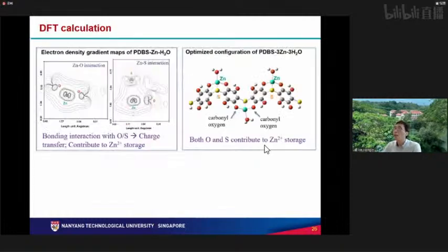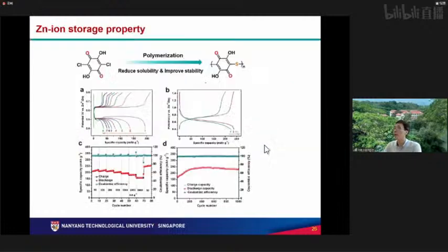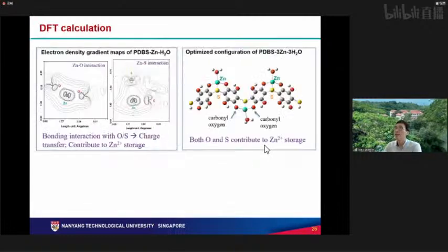And so there is a lot of simulation and characterization to try to understand what the advantage of the polymers is and how the zinc interacts with the functional groups. Okay, and we found that they can do these electron density gradient maps, to see whether there is a charge interaction between zinc and oxygen, and between zinc and sulfur, to confirm that, okay, there are some electron clouds shared by those two. So that means we may have a bonding interaction between this oxygen and sulfur with the zinc, causing charge transfers, so contributing to zinc ion storage.